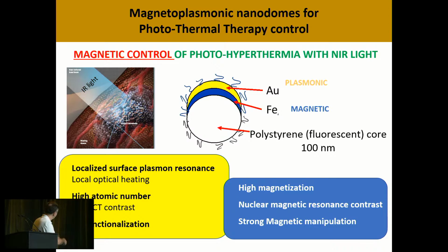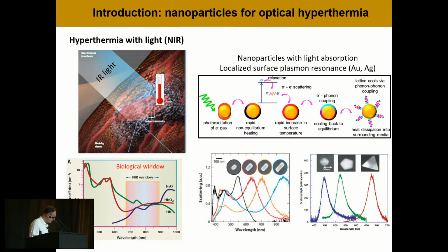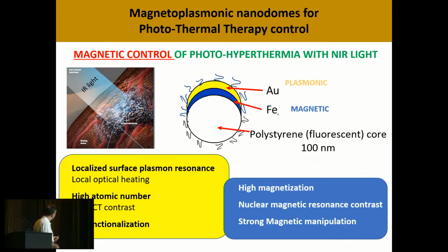It has a high atomic number, which can be used for X-ray contrast tomography, and it's very easy to biofunctionalize. And iron has a high magnetization and a nuclear magnetic resonance, which can be used for MRI. And because of the high magnetization, it can be easily manipulated using magnetic fields. And what we want to do with this is magnetically control these nanoparticles to do photohyperthermia using near-infrared light.